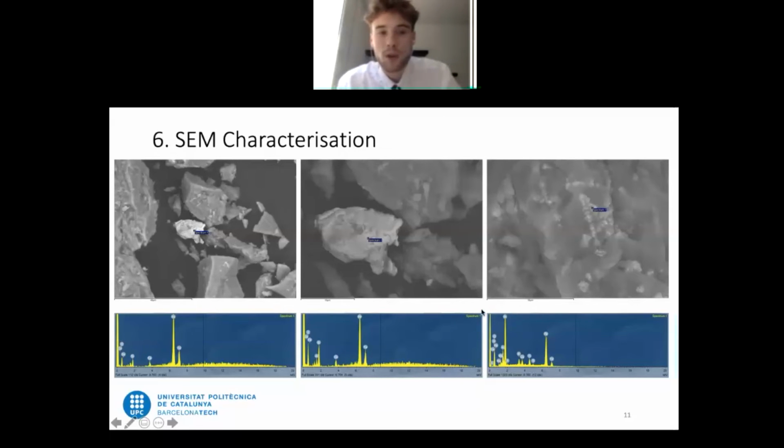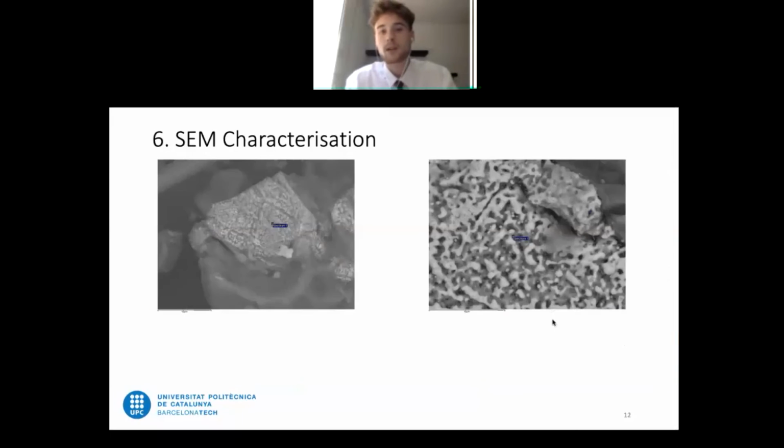So essentially what we can get from here is that when we're viewing this particle at a lower magnification, these smaller abundances of iron will coalesce together and effectively act as one greater particle of iron. This is a factor that could have a major effect on the analysis of the optical spectra, as it's been determined that metallic iron has a massive effect on the optical spectra of the reflectance that's produced.